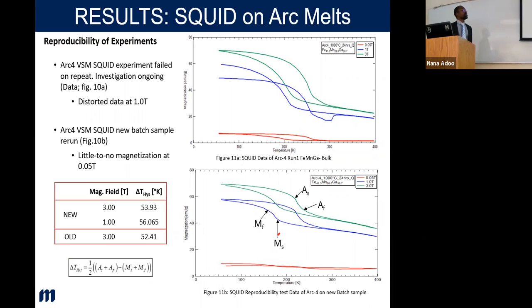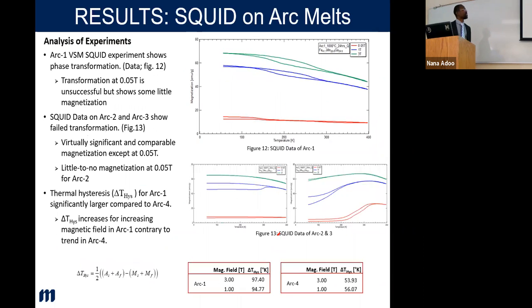the interesting thing that I found also is that I could get hysteresis as low as 52.4, and that was really interesting because in all these materials, the range of hysteresis I've been seeing was between 80 and 90. And so this was really an improved or significant change in whatever I'd seen or I'd done.